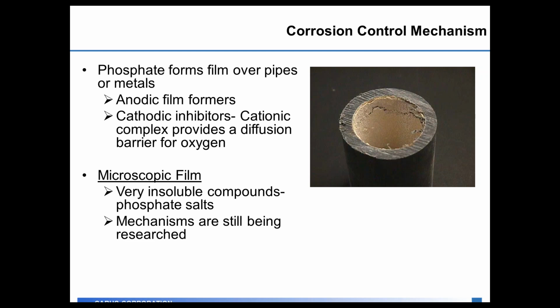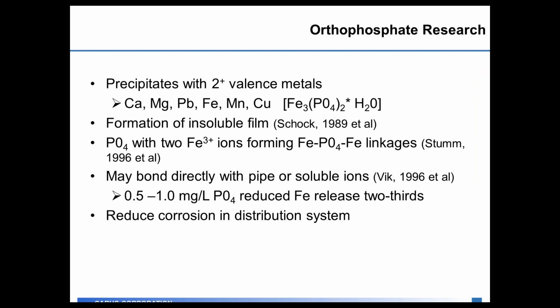The research has shown that these thin films are very insoluble phosphate salts, and we are still doing research today on how these films form, how long they stay active, and what are good levels of phosphate to feed in the distribution system. The orthophosphate research that you can find out there today talks about orthophosphate precipitating with the 2+ valence metals. So that would be the calcium, the magnesium, the lead and copper pipe, and the iron and manganese you would have in your distribution system. Michael Schock did a lot of the original work on the formation of the insoluble film out in the distribution system. What we know is that we bond directly with the pipe wall itself or with some of the soluble ions in the drinking water itself.